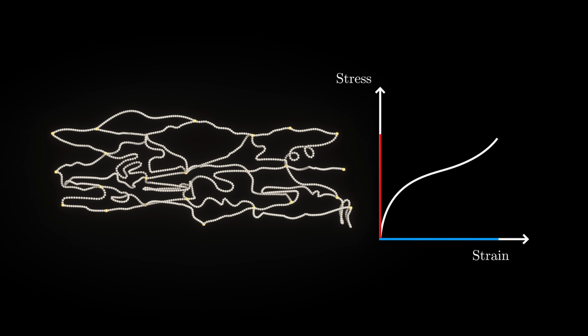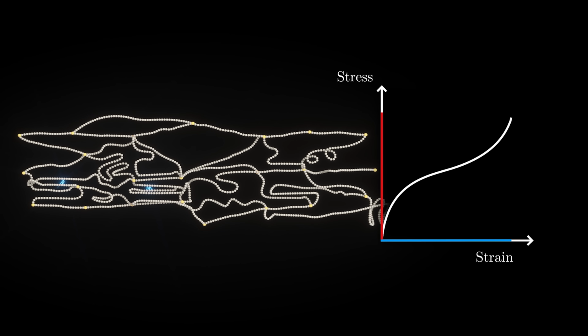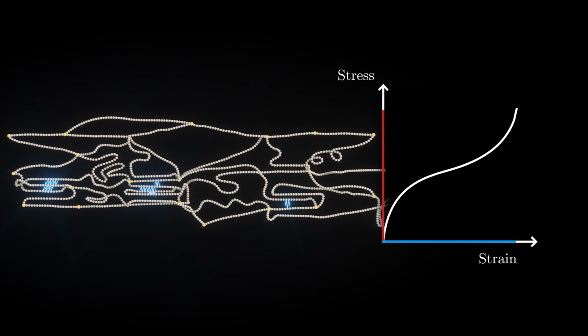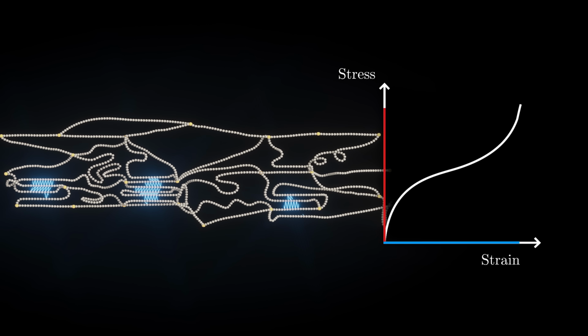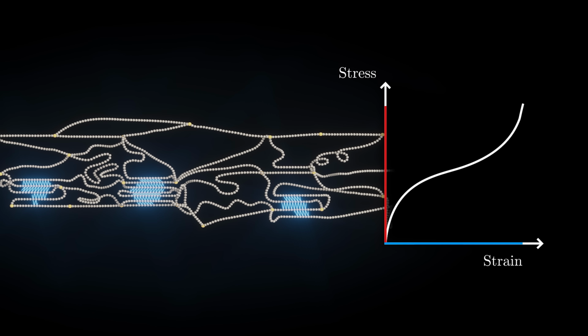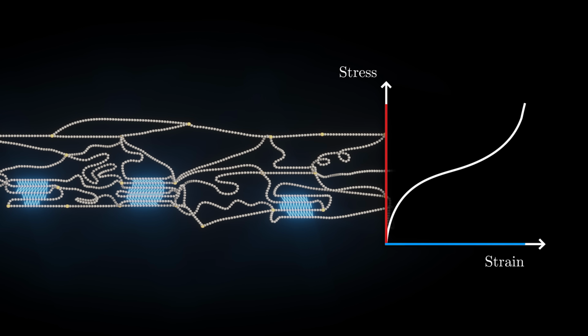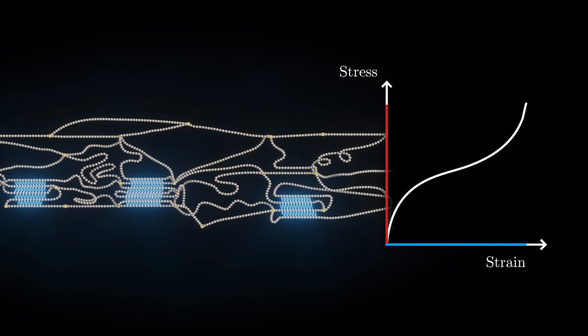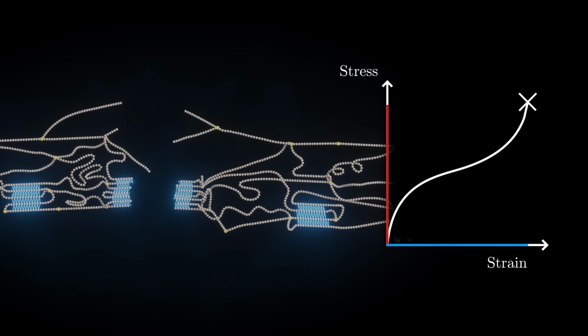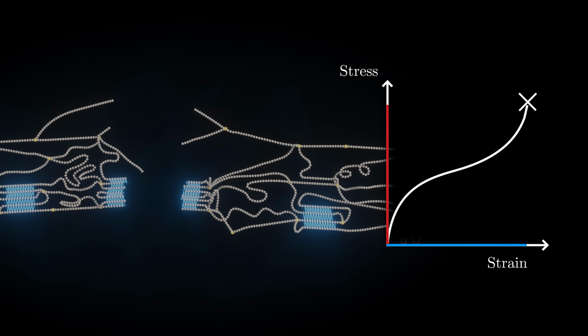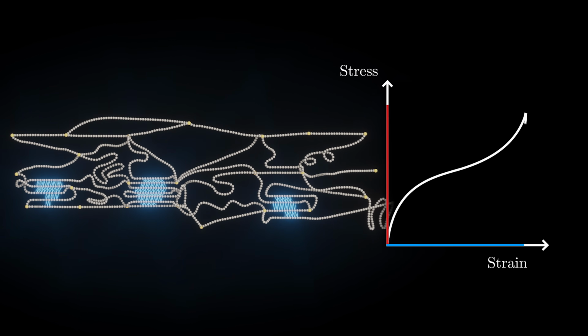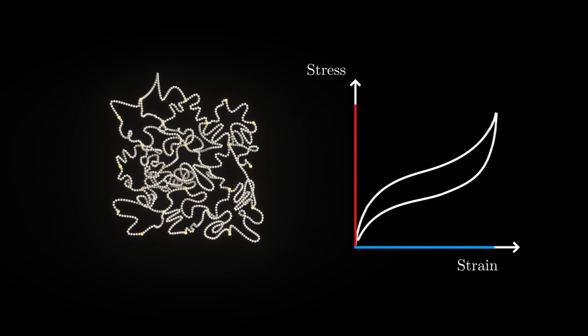That section where it gets really hard to pull it any further and it gets hotter, that's right where rubber starts to crystallize. The rubber warms up because as those new bonds form, they release a bit of energy as heat. Then, if you keep stretching it, you get to the point where the crystal can no longer hold it, and it breaks. But something strange happens if you stop right before that fracture point. Then, the rubber bounces back, but on a lower curve.